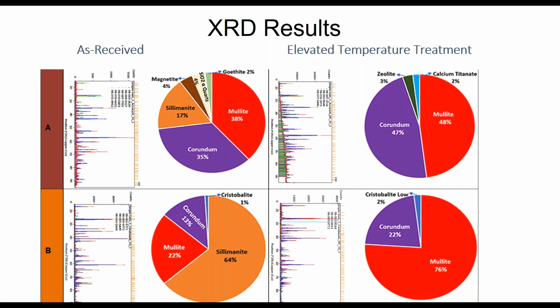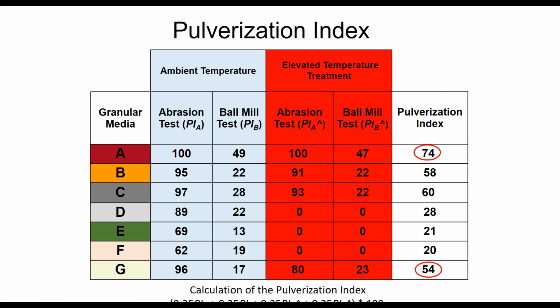And then after elevated temperature treatment, that elevated temperature treatment in the AFS study was 1450 degrees C, which is typically the iron processing temperature. And what you see, some of these hard compounds, mullite, corundum, sillimanite, these are in the top 12 hardest materials known to man. And they change in proportions when they are treated at elevated temperature. That also affects what we call the pulverization index. This is a measure then of durability as we look at ambient to elevated temperature treatment, from abrasion to ball mill impact. And to keep things simple in our study, we weighted things rather equally.